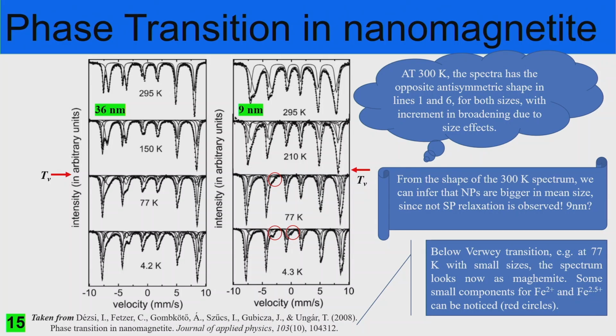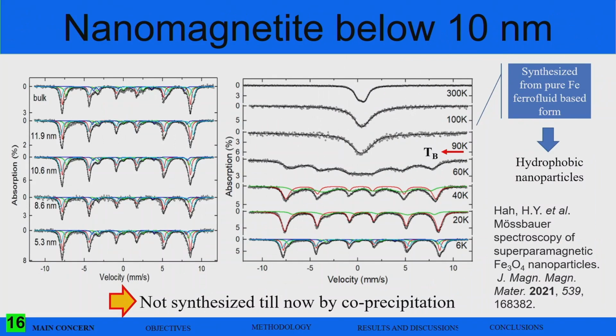Of course, below the Verwey transition, for example at nitrogen temperature with small sizes, the spectrum now looks like maghemite because of the inversion, as you can see here. But we have additional components, iron 2+ and iron 3+, as Jean-Marc has marked in his presentation. The problem with particles smaller than 10 nanometers is the oxidation that can occur through the co-precipitation method, and we cannot control that. Even using an inert atmosphere, the surface can oxidize, because the organic agents used for functionalization can also affect the chemical surface composition, and we will have a continuous oxidation. Of course, this matters at the time to perform the adsorption experiments, because we will have iron 2+ and iron 3+ on the surface, which will coordinate with the heavy metal. This is a really important thing that we have to take into consideration.